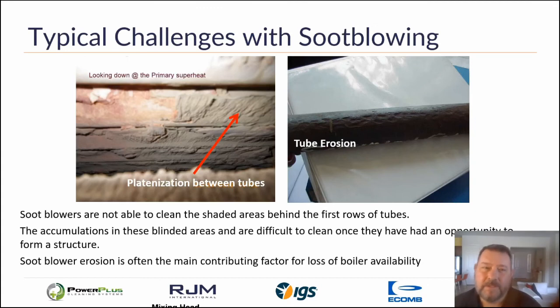As I just mentioned, the typical challenges with soot blowing are the effects of platenization between the tubes where the soot blowers don't have direct access. Also, aggressive soot blowing or soot blowing in general over time can cause tube erosion and pitting that will eventually lead to thinning of the tubes and tube leaks.